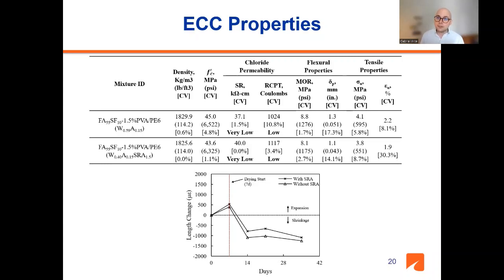An interesting thing about the shrinkage reducing admixture, we not only are using it in this research for the purpose of reducing shrinkage, but also we have found out that this admixture was helping us with the distribution of the fibers. We don't really understand the mechanism of action, but when we use the SRA, it was helping us to prevent fiber clumping in these systems.